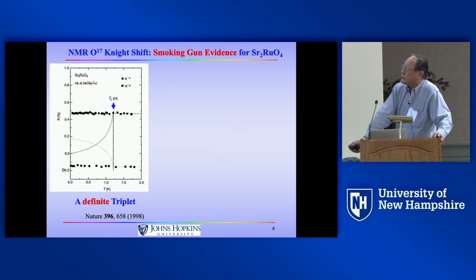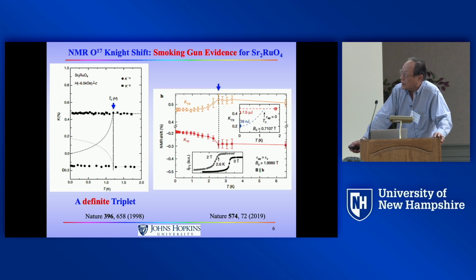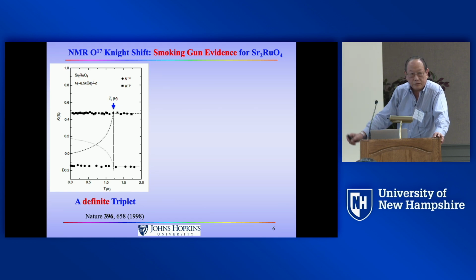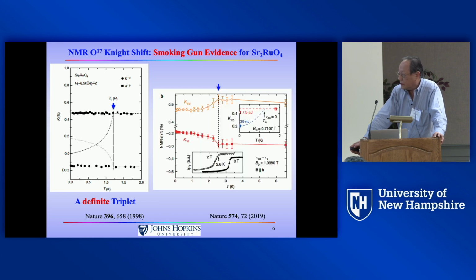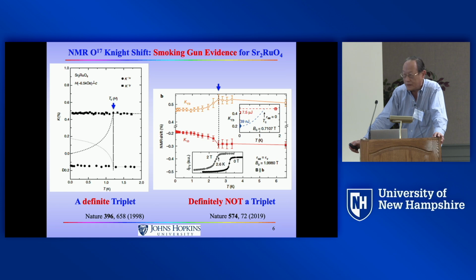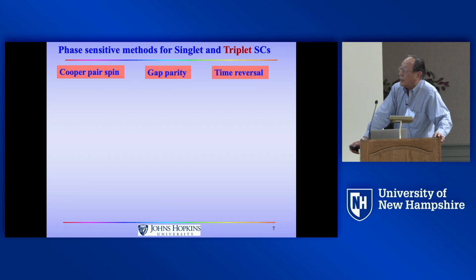The NMR Knight shift used to be the smoking gun evidence for strontium ruthenate as a triplet, because they measured the Knight shift and there was temperature independence across Tc. So there's no change. This was considered the smoking gun evidence for strontium ruthenate to be a definite triplet. That was 1998. In 2019, they made better samples and did better measurements. It showed very distinct temperature dependence. Overnight, it died. Strontium ruthenate is no longer considered a triplet superconductor because of the Knight shift temperature dependence. So I don't want to use these methods, because they show it's not reliable.